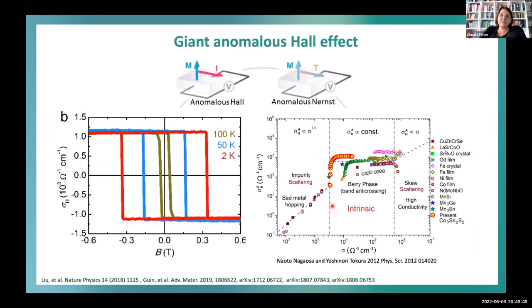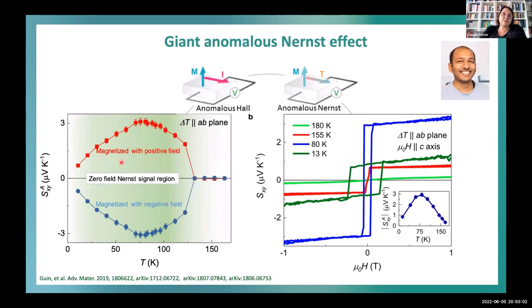And again, we do the same anomalous Hall effect. Nice. Now we have a nice hysteresis since the material is hard magnetic. We can show that it's intrinsic because the values are lying quite well in the intrinsic range. And we measured the Nernst effect, a giant Nernst effect. Now we can even switch the Nernst effect, since we have the hysteresis also in the Nernst effect in this material, and also very large values. So you see, I showed you already three examples, and all three examples immediately showed the nice effect.